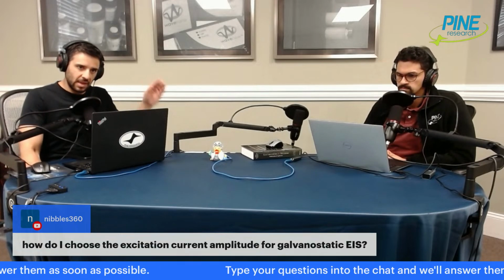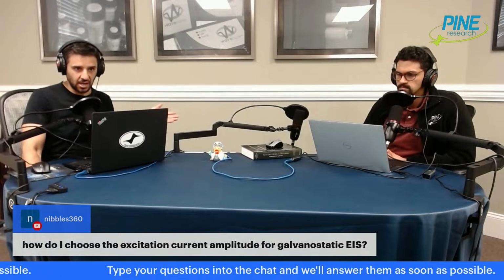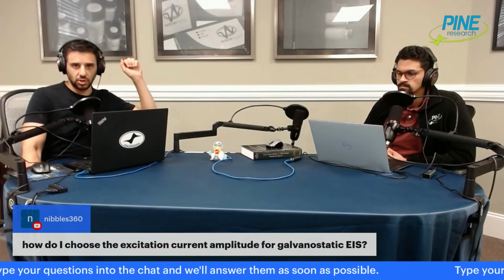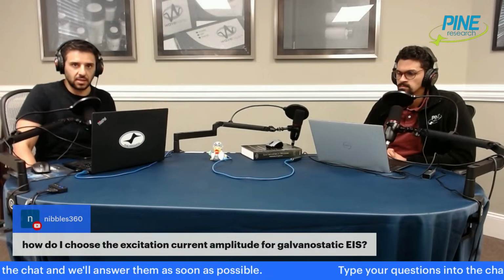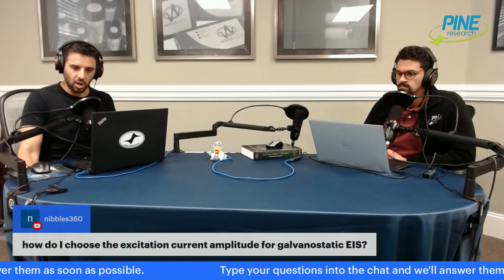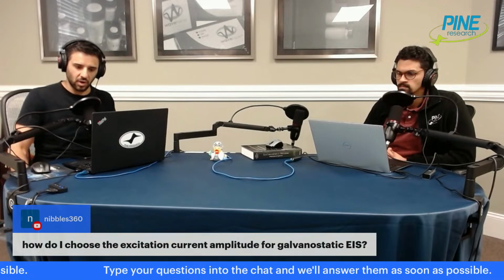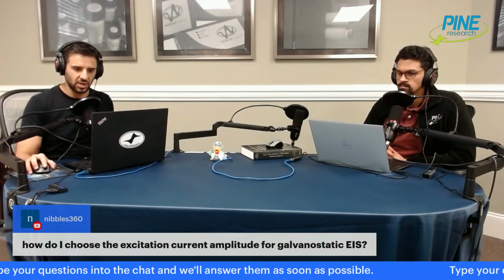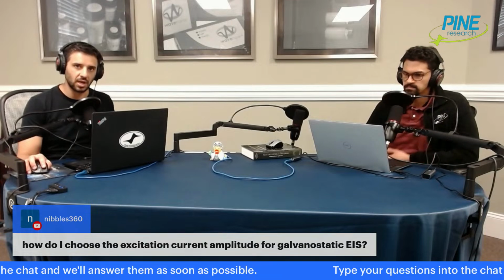You should be able to find that place. Roughly speaking, the minimum amplitude at which you get good-looking data, but it's not too high that you're not linear, you're not stable, basically. But you should be very cautious with galvanostatic in general to start somewhere small, because that is a situation where too large of an amplitude, you could damage your system. Haven't you mentioned also that if you have an idea that your system has about 1 kilo ohm of resistance, well, if you put 1 milliamp in, you're going to get like a volt swing. Yeah. You can use Ohm's law for that too.